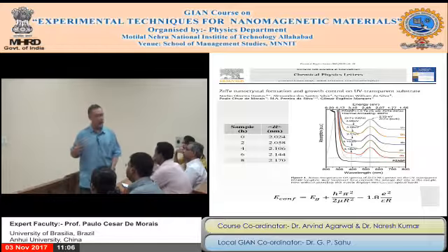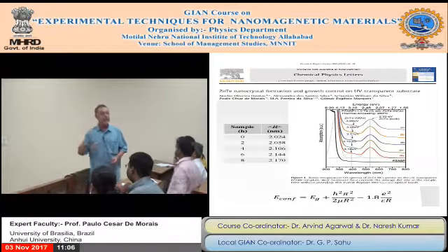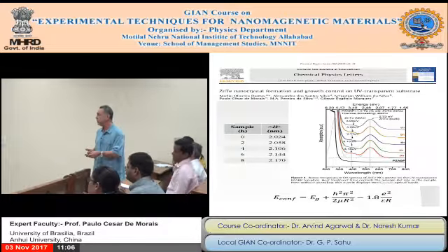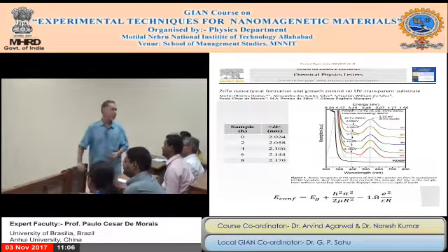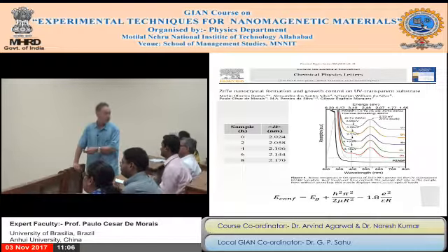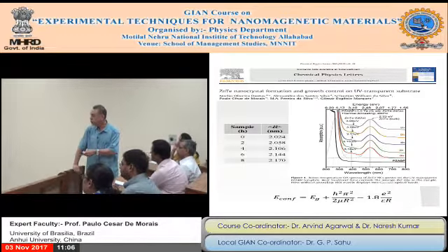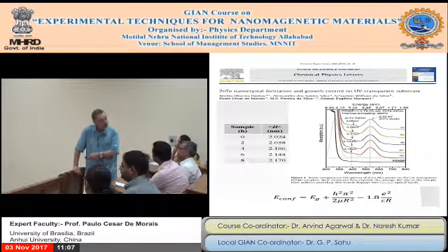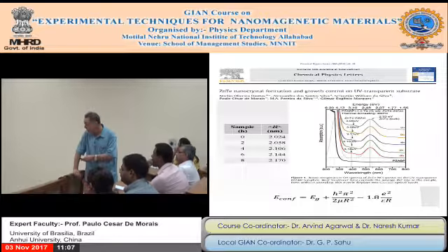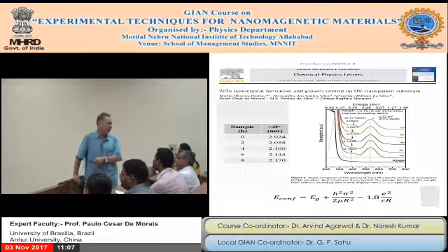You excite your sample with high laser intensity, and you generate a lot of carriers inside the dot. And the density now is high. And then you need to take into account the effects I mentioned to you, the band bending and the band gap renormalization. At the end of the day, the equation is much more complicated than this.